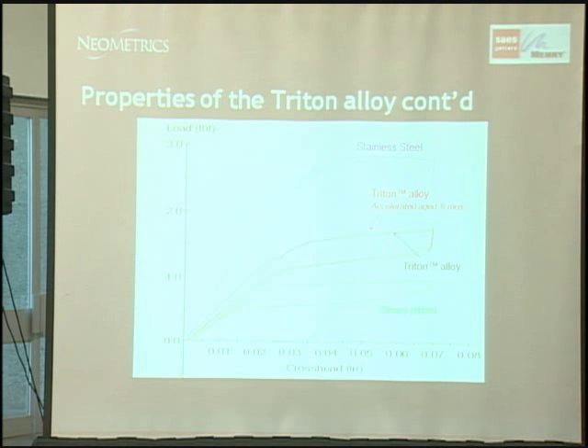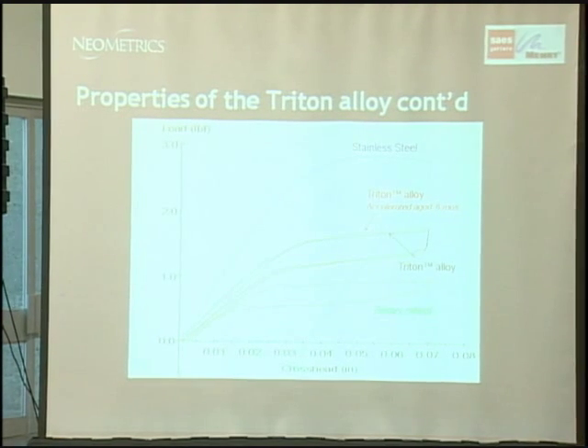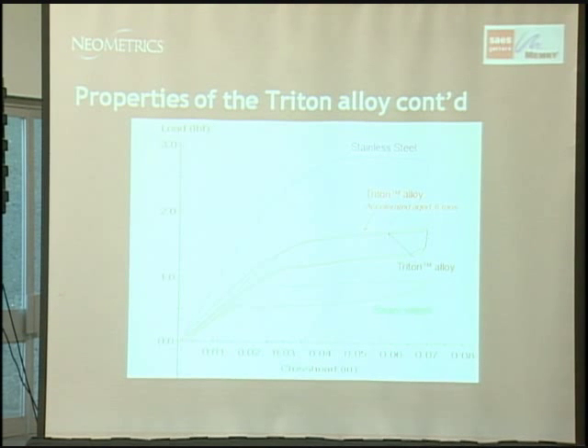Getting back to the effect of strain on stainless steel, this again is a 3-point bend test showing the loading of the stainless steel to a maximum strain level, and then when the load is released, the wire does not go back to its original 0 starting point. That's the plastic deformation that we talked about earlier. The Triton alloy falls right between stainless steel and binary nitinol, with a hysteresis curve similar to binary nitinol, but going back to a 0 starting point within 7% strain.